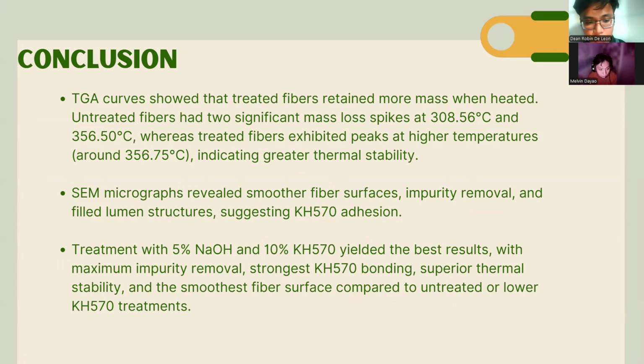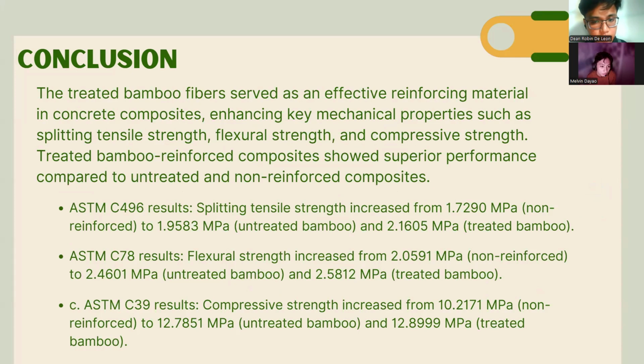SEM micrographs revealed smoother fiber surfaces, impurity removal, and filled lumen structures, suggesting KH570 adhesion. And the treatment with 5% NaOH and 10% KH570 yielded the best results with maximum impurity removal, strongest KH570 bonding, superior thermal stability, and the smoothest fiber surface compared to untreated or lower KH570 treatments. The treated bamboo fibers serve as an effective reinforcing material in concrete composites, enhancing key mechanical properties such as the splitting tensile strength, flexural strength, and compressive strength.